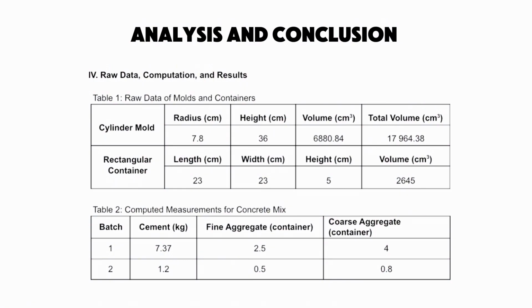Despite this, slight variations in consolidation may have affected the uniformity of the samples. To improve the mix, a material engineer should adjust the water content within ASTM C192 guidelines or incorporate a superplasticizer to enhance flowability without increasing the water-cement ratio. Proper consolidation techniques such as systematic rodding and tapping are also recommended to minimize air voids and ensure uniform material distribution. Additionally, the calculated shrinkage factor of 1.25 emphasized the importance of considering volume reduction during drying to prevent cracking